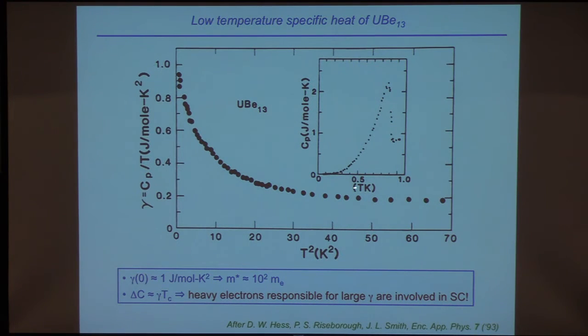And so here's specific heat versus temperature. You see this jump. And this jump is of the order of gamma times Tc, which is close to what the microscopic theory of superconductivity would lead you to suspect. And this tells you that the heavy electrons responsible for the large gamma are also involved in the superconductivity.